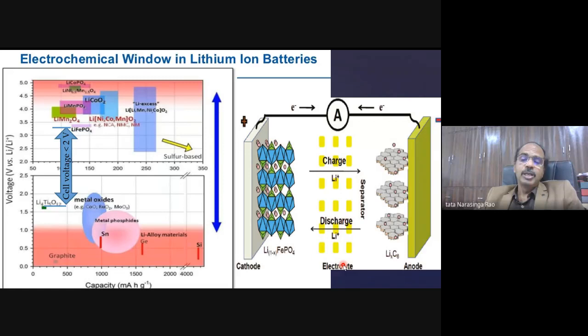But what happens is, if you want a higher voltage, you can see the red region where the electrolyte itself starts decomposing at the electrode. You start getting dirty layers on the electrode, so your electrodes may not work for a long cycle life. So LiFePO4, lithium iron phosphate, which is used mostly in electric vehicles, is in the white region. It is safe because the electrolyte decomposes above 4 volts, but we are only at about 3.2 volts. So we are safe here. The white range is safe.